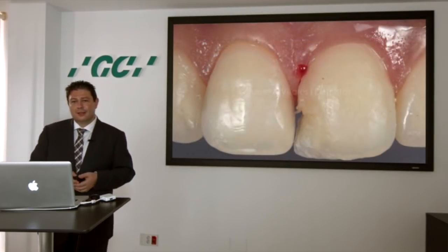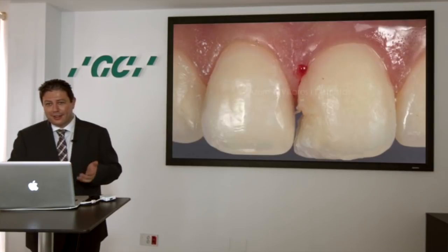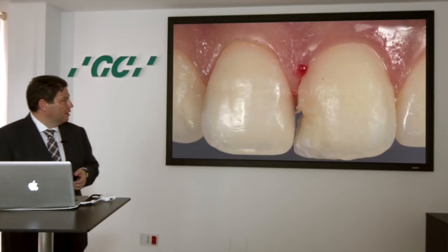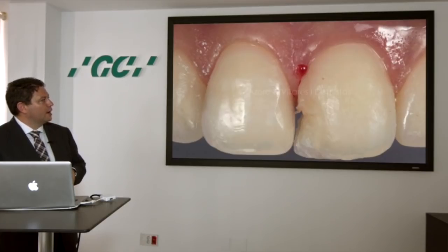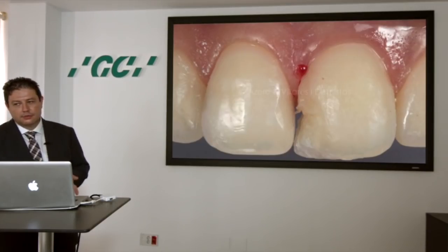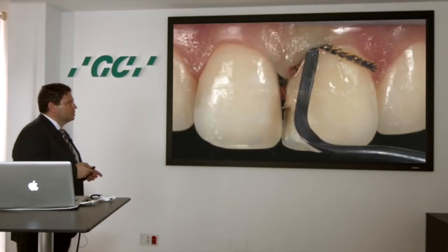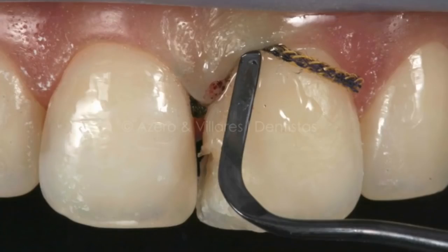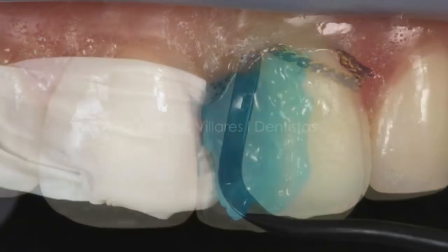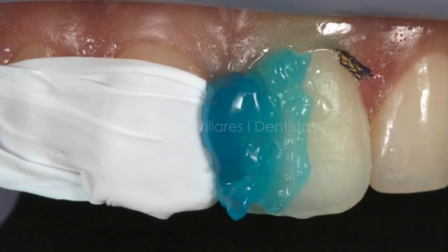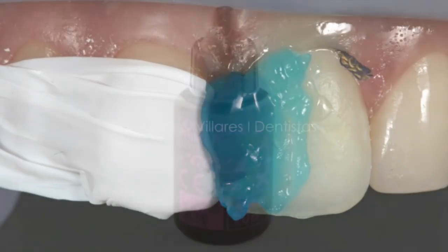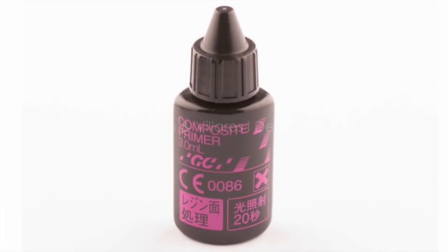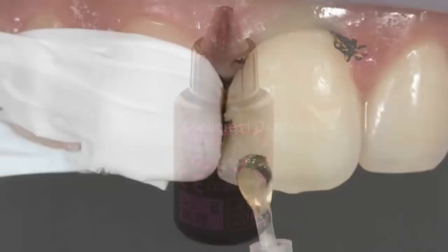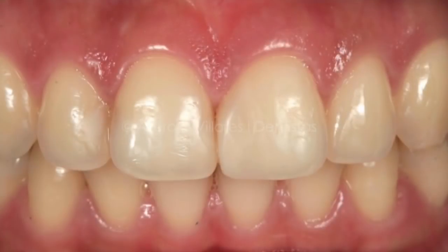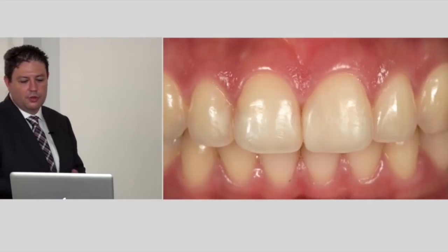This happens to everybody that works. You are working, you don't put the rubber dam there, and you are working near the gum, and this starts bleeding. No problem. There are some tricks, you can put a cord. The most important thing is that after you need to etch the preparation, just to clean the surface, and use some resin that allows you to complete your restoration without any problem, to finish the restoration so that it has a proper result during a long time.